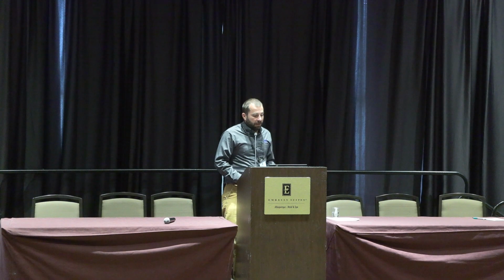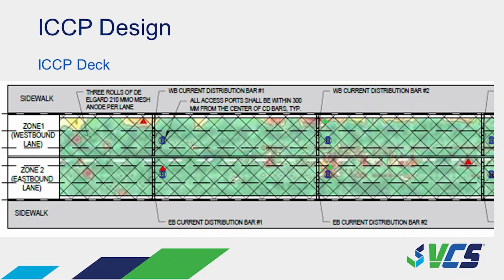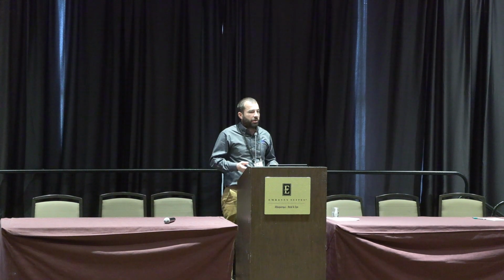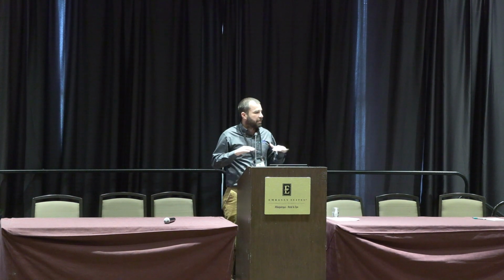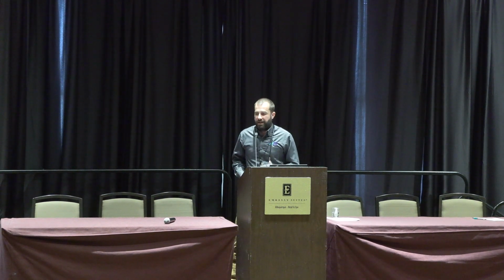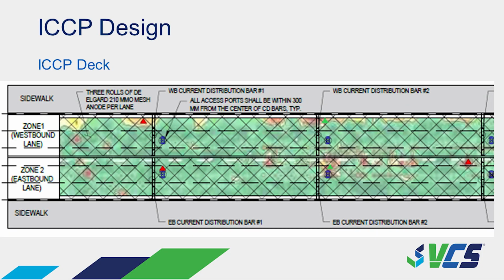Effectively, we designed an impressed current mesh overlay for the deck. They would hydro-demo the deck, put down an impressed current mesh over the deck and recast a new overlay. That mesh on the deck would provide cathodic protection for the entire top mat of the reinforcement. It would throw some current down below to the lower mat, but because of the salt application on the top, we're really more concerned about the top mat. This is an image showing what that looks like, our connection points, the mesh over the lanes and so on. It's just a 2-lane structure.